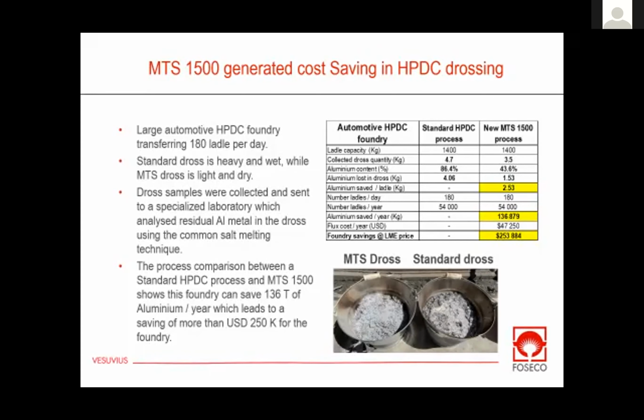So I have calculated there 2.53 kilogram of pure aluminum that was trapped in the dross in that foundry we are able to save. When we multiply this by the number of ladles that this foundry is processing, this is a very large high pressure die casting, it represents 136 tons of aluminum potentially saved. This is a huge number, and we didn't change anything else.